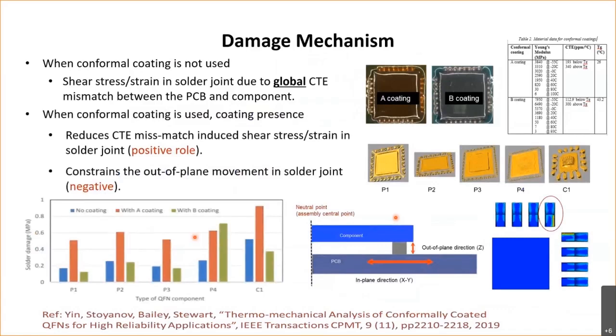Here we could see different coatings. The conclusion here is that you've got to be careful with some of these coatings. Here we can see damage in solder joints with no coating. So the lower the damage, the better. But with this particular coating, it's interacting with the solder joints. There is an interaction there and it's leading to further damage. So coating B was better here, coating A was problematic.